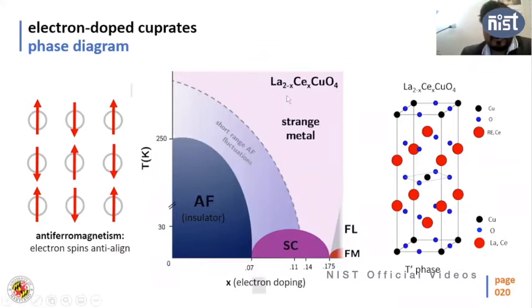This is the phase diagram of this LCCO material, temperature versus doping. If there is no cerium, this is the parent compound, which is an insulator. It is also an antiferromagnet. In copper, the spins are aligned antiferromagnetically, which gives antiferromagnetism. With doping, if you increase the cerium concentration in this material, what happens? This Néel temperature, this blue regime, decreases and vanishes around doping 0.07, then the superconductivity emerges.